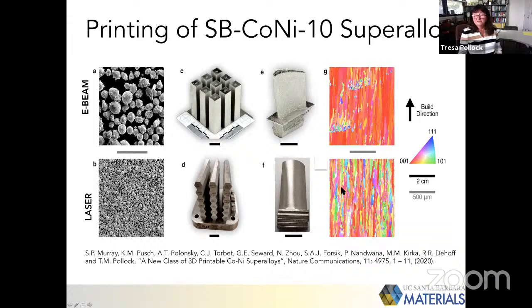Now I show here the structure of the material from the laser versus the electron beam printed material. And so in the case of the electron beam printing, one uses a higher preheat. So we have a tendency for more columnar structure. And earlier I showed you some lack of fusion defects that caused grain nucleation. This is not a lack of fusion defect, but it certainly is a transition from columnar to equiaxed. And so this is not what we would predict. And so we're in the process of making data sets to really understand the details of why this transition happens. And one can see in the lower preheat laser material, a more columnar structure.